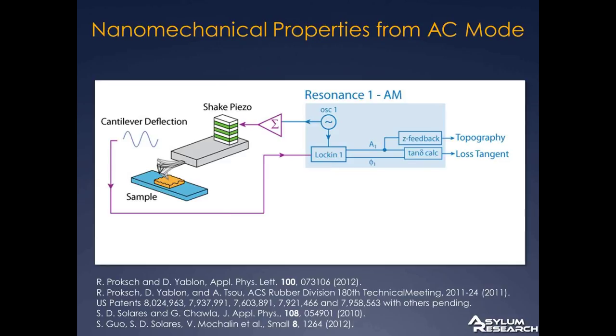Now, that amplitude and phase will be used to calculate the loss tangent. The amplitude signal also goes into a feedback calculation and controls the tip-sample distance and gives us an image of the sample topography. So out of that first mode, we get topography and loss tangent. And because we are controlling the amplitude, we call that an amplitude-modulated or AM signal.